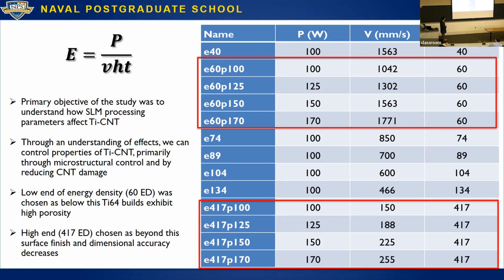You might wonder, why don't we just go to very high energies and have it very molten, and you completely eliminate that problem? In terms of our nanotubes, we were a little worried that at very high energies we'd increase reactivity. And actually, one Chinese group beat us by maybe 6 months or so publishing this work. In their composites, and I'll talk about it in a couple of slides, they essentially destroy all of their CNTs in the first place.